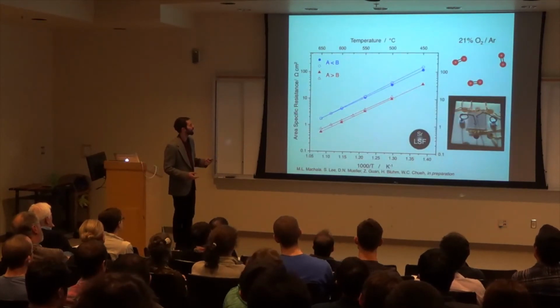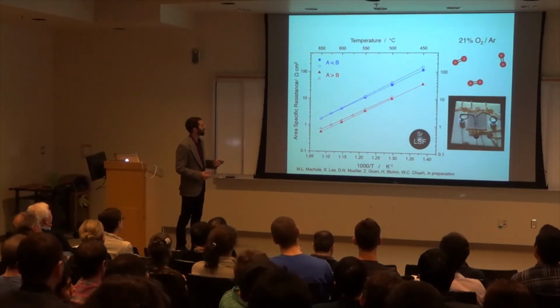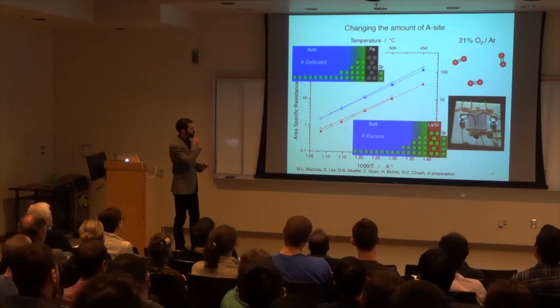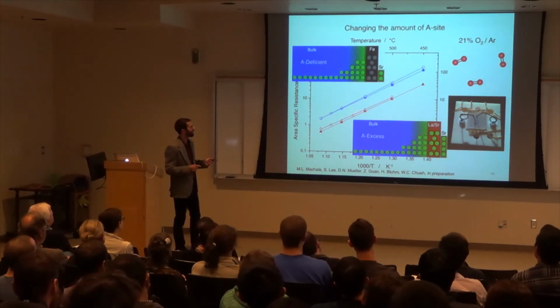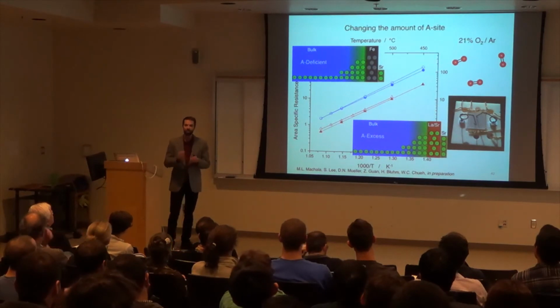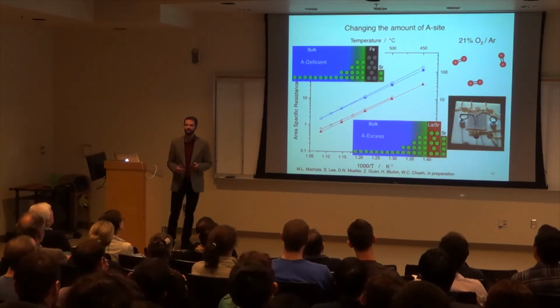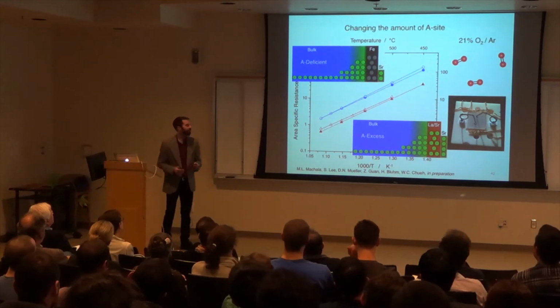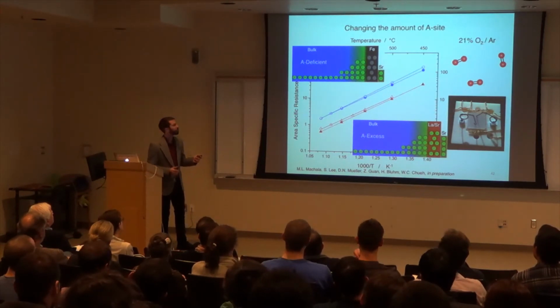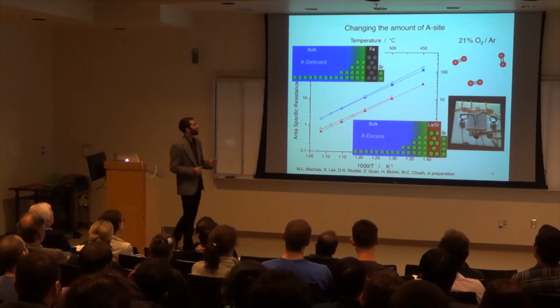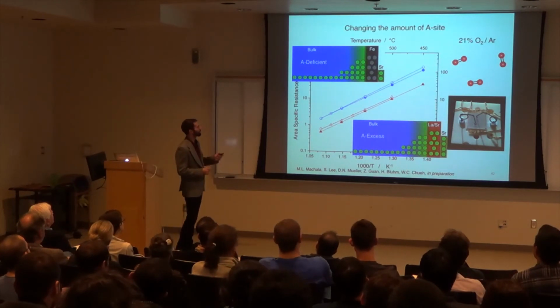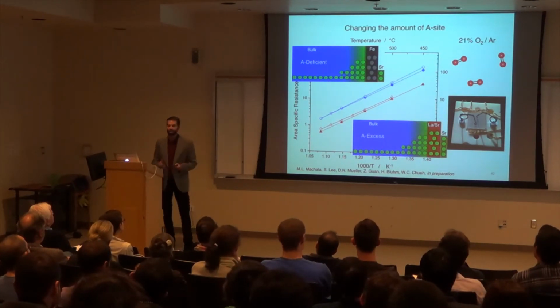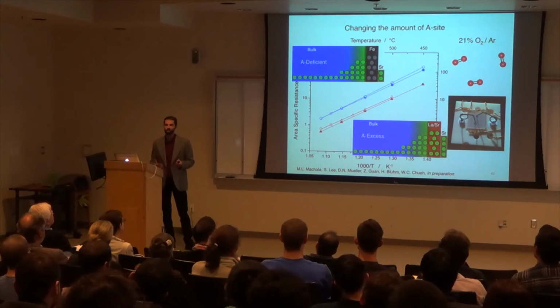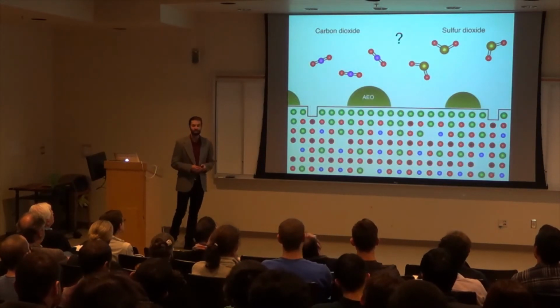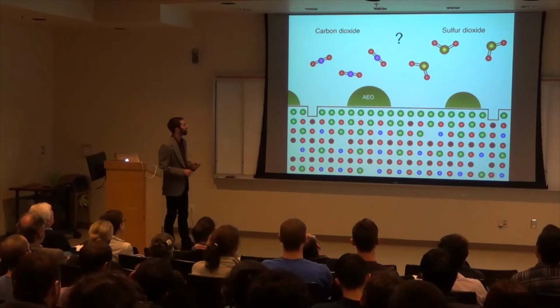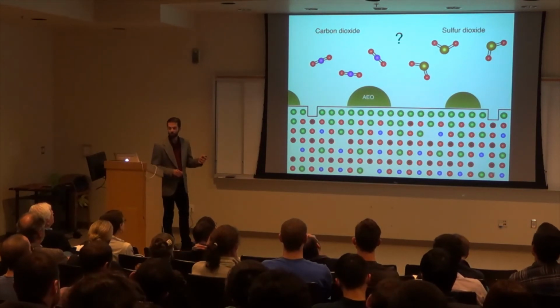And so now I return to these two surfaces. One thing I failed to mention already is that we have these two lines on here, and these two different measurements, to show that we can reproduce these measurements quite well. Right now, let's focus in on the surfaces of these two material systems, not just in a very clean environment, but in a real environment where we have trace gases such as carbon dioxide and sulfur dioxide.